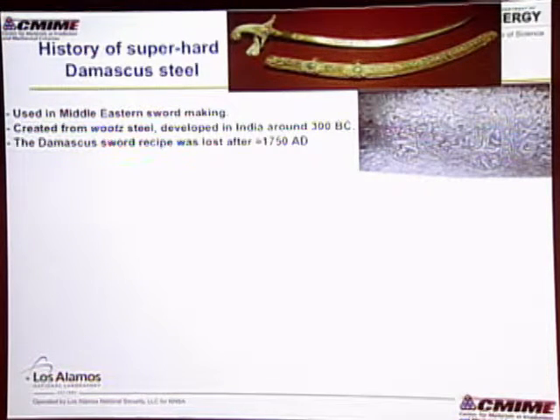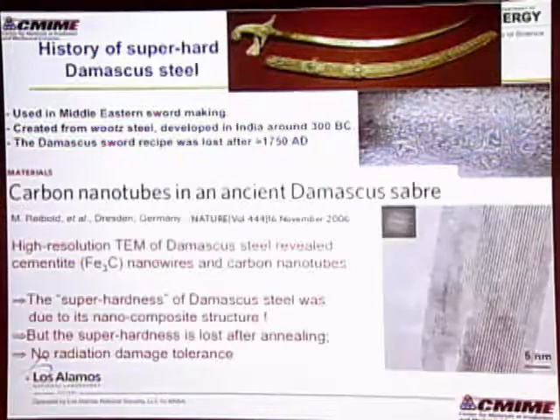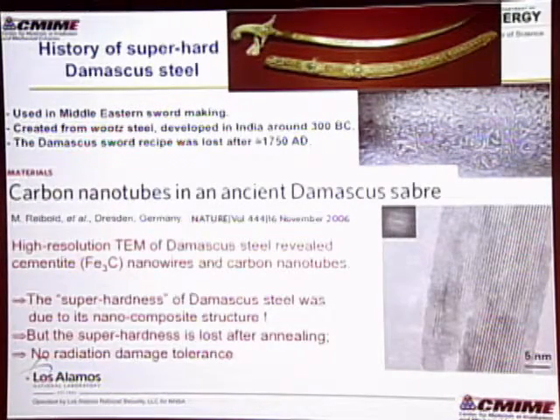Multi-layered materials have been used for a long time in the form of Damascus steel. It was used in Middle Eastern sword making, developed around 300 BC in India. These are also called pattern welded steels. You get these very nice swirl patterns from the processing. But the sword recipe was lost around 1800. Nobody knows exactly how these swords were made. But just recently, some researchers in Germany took a chunk of one of these ancient swords, dissolved it in acid, and were left behind with a whole bunch of carbon nanotubes and also cementite nanowires.